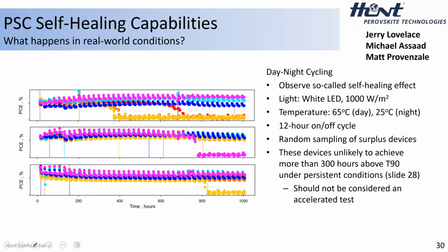Now, another aspect of durability is that typically when we do durability measurements, they are accelerated lifetime tests, meaning we are stressing the cell in a way that hopefully we can collect a vast amount of information on how the cell will perform over time, but in a short amount of time. And so in this case here, we wanted to more replicate the day-night cycle. So we hold our cells at 65C and 1 sun throughout the course of the day for 12 hours, turn that off, cool to 25. So off for 12 hours, on for 12 hours, what happens?